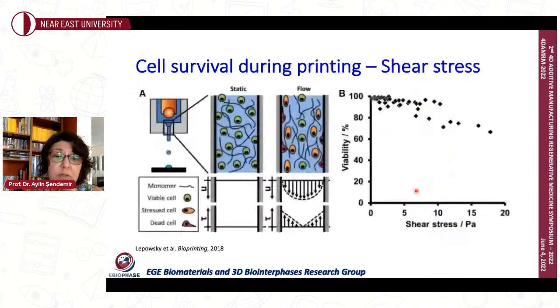So therefore, particularly some simulations or in silico representations of the printing process would be very helpful, because in the literature it is known how much shear different cell types can bear. And even some shear is helpful for cells. It does trigger some types of differentiation, or it might even increase cellular viability. But above a threshold level, shear stress definitely would lower your cellular viability, would change your cellular characteristics, and in the end, it might even cause your cells to die.